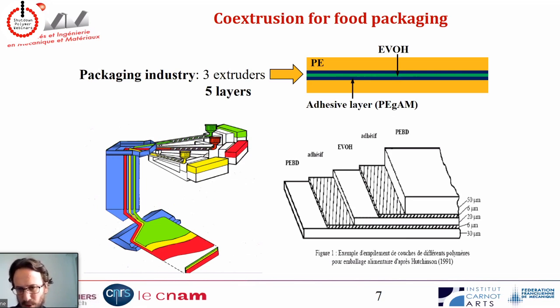So that's the basic idea, and it works really well, but there is one problem, which is that PE and EVOH, they don't like each other, so they don't stick to one another. So if you make a film of these two polymers, the 2 layers will simply peel off really easily, they will detach, and so your film will not have good mechanical properties. So what you have to do is add a 3rd layer, an adhesive layer, which is usually a polyethylene with some maleic anhydride grafted molecules on it. And it will make the polyethylene and the EVOH bind together. So actually you are not using 2 extruders, but 3 extruders to make a 5 layers film.